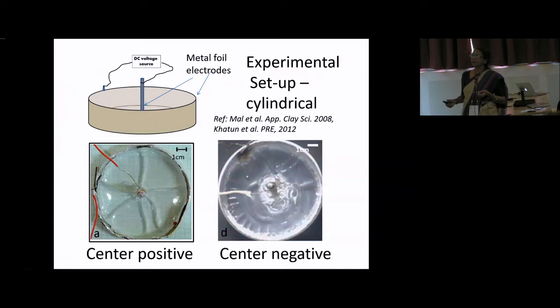And what happens when a field is applied is like this. If the center terminal is positive, the cracks appear from the center, these are the cracks, and they move to the periphery. And if you have the oppositely directed field, that is the periphery is positive and the center is negative, in that case also the cracks appear from the positive. In this case, that is the periphery. So the cracks have started here, but as you see, they do not go right up to the center. This is what we had earlier.